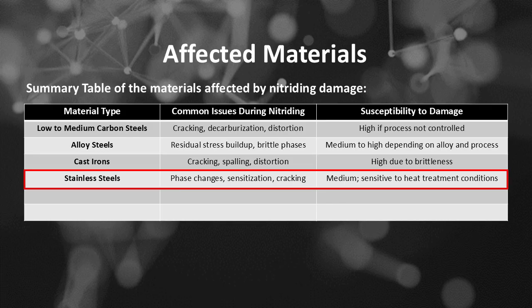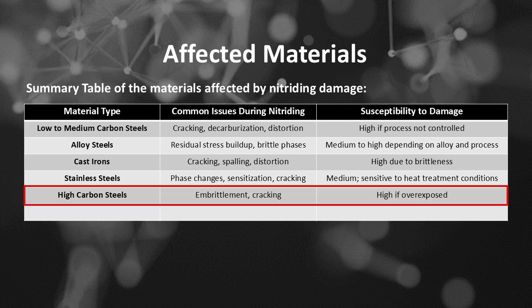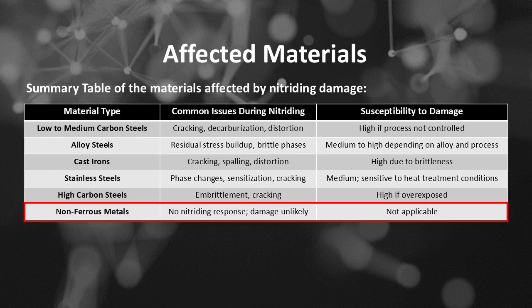If material type is stainless steels, then the common issues during nitriding will be phase changes, sensitization, cracking, and the susceptibility to damage will be medium, sensitive to heat treatment conditions. If material type is high carbon steels, then the common issues will be embrittlement, cracking, and the susceptibility to damage will be high if overexposed. If material type is non-ferrous metals, then the common issues will be no nitriding response, damage unlikely, and the susceptibility to damage will be not applicable.